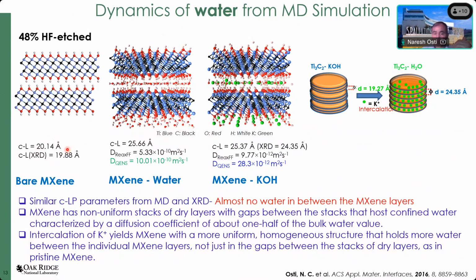But once you put the metal ion together with the water molecule, the C lattice parameter that you obtain is nicely matched with that of the XRD C lattice parameter. It means that once you intercalate the metal ion between the layers, that metal ion takes the water together with it and keeps it in between the layers. That's why we have a significant reduction in the water diffusivity in metal ion intercalated MXene compared to the pristine MXene. That's what we found in this particular example.